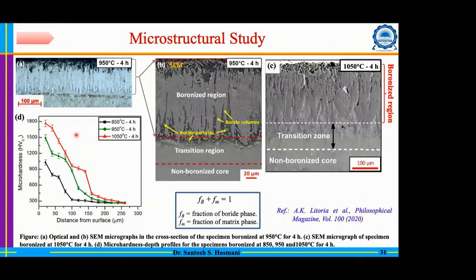Actually, if you notice carefully, at very high magnification there are open gaps, especially look at figure B. And these open gaps are nothing but the matrix. That means that region has not yet been transformed to boride. You can see that this matrix is there even up to the surface. That means you still have a trapped matrix region, which is unable to transform into boride entirely. And this situation is aggravated, or the proportion of matrix is greater, at a lower temperature.